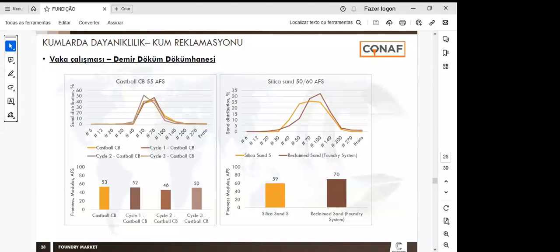Castball maintained its sand distribution curve and GFN, while the silica sand became finer, as seen in the results obtained in the laboratory with the ball mill. And then we can conclude that the attrition test in the laboratory shows a good correlation with the practical results in a foundry, okay? And Castball presents high durability in the laboratory and in practice too.